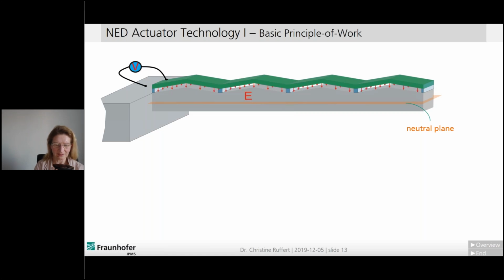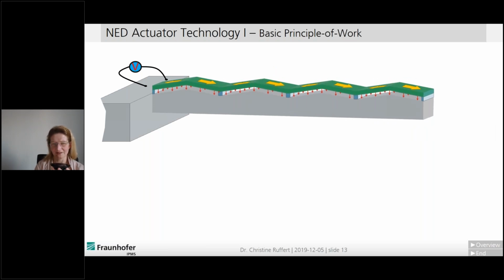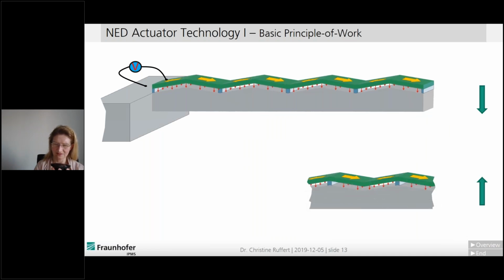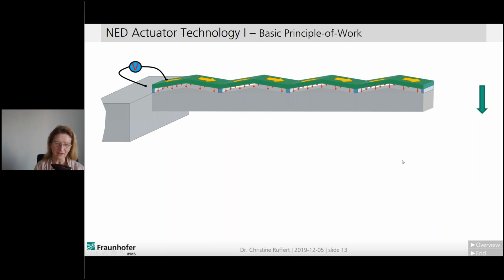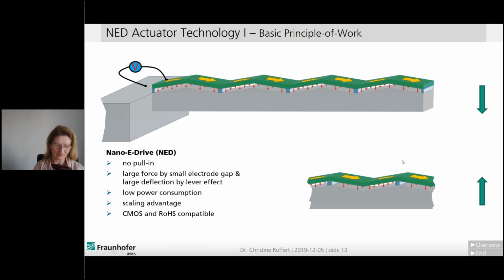And we define a neutral plane. We apply a voltage between the upper and bottom electrode, and forces are created that try to bend the upper electrode down, nearer to the bottom electrode. And as I explained just a minute before, the cantilever will bend. You can also do it the other way around: you can put the spacer on the top instead of in the valleys, and you will create a force which lifts the cantilever upwards. So with this system, we have no pull-in forces. We can create very large forces because we can create really small air gaps of only a few hundred nanometers, and we can achieve a very large deflection by using the cantilever effect.